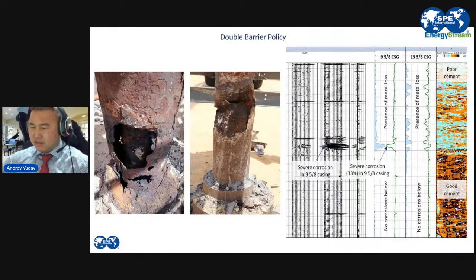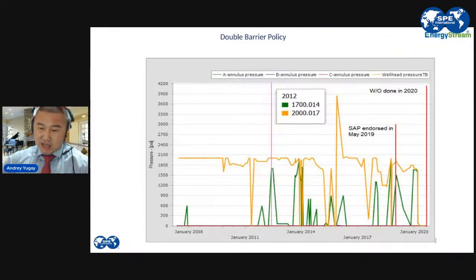And also we can see that the 13 3/8 is corroded all the way from top to bottom, but the corrosion, the metal loss, stops at exactly the same depth where we have the corrosion of 9 5/8. So putting all this together, we got the puzzle: the corrosion happened in between these two casings, 9 5/8 and 13 3/8, at the interface between good and bad cement. So corrosion can happen in between casings, and corrosion can happen internally, from the internal side of the casing. So look at this pressure survey.